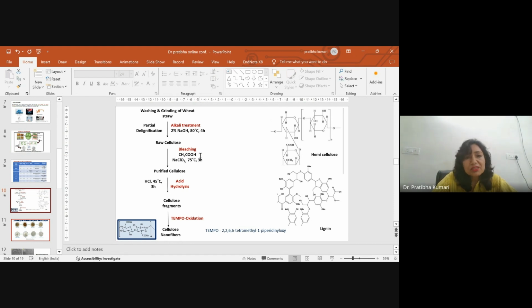And after we repeated bleaching 3 times, the hemicellulose is removed. There are some crystalline portions in cellulose and there are some amorphous regions. So the amorphous region gets hydrolyzed or removed by the bleaching. We'll get the purified cellulose. Then we perform the acid hydrolysis. So after acid hydrolysis, we'll get small fragments of the cellulose. To make it further refined and further smaller in size, we perform TEMPO oxidation. After oxidation, we'll get the fibrous structure of the cellulose.